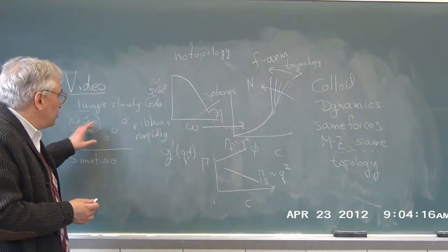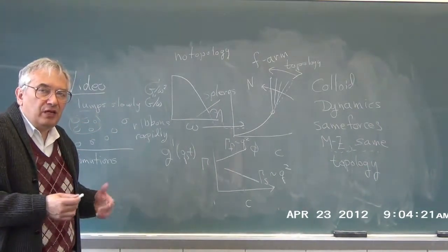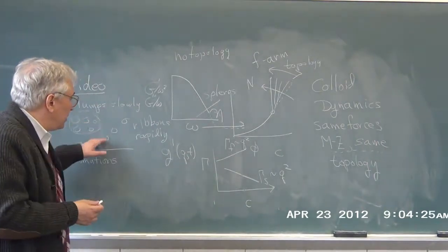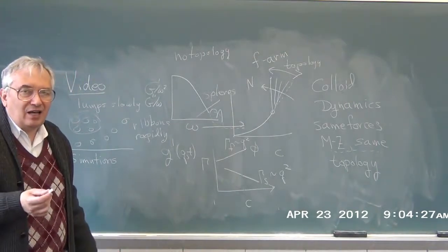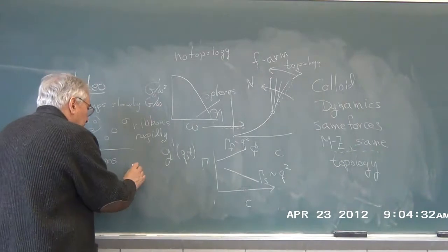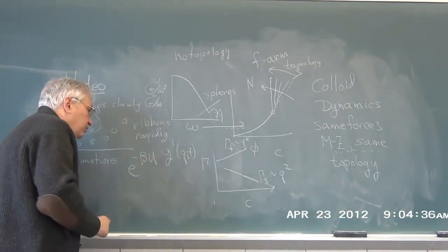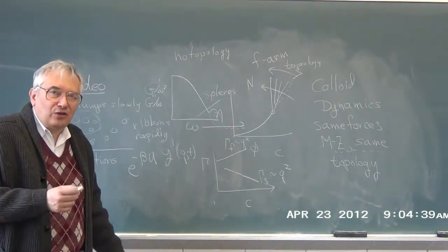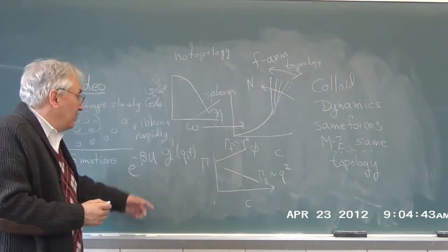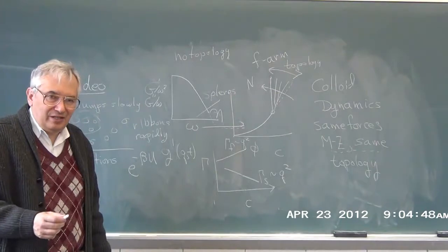And this becomes, you don't see this at high temperature, but at low temperature, meaning for spheres, high concentration, you do see this dynamic effect. Oh, aside, we have hard spheres. The potential, the Boltzmann or Gibbs factor e to the minus beta u is either 1 or 0 because the potential energy is either 0 or infinity. Therefore, e to the minus beta u is temperature independent.